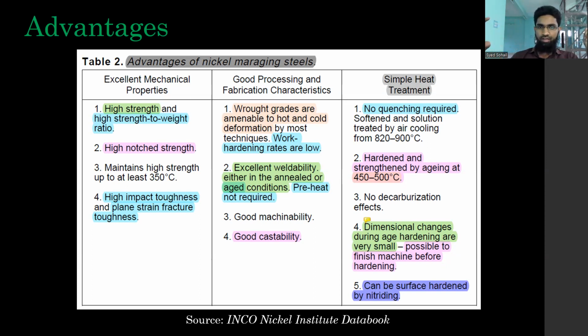You have no quenching required. Once it is solution treated or aging treated, you cool it through air cooling and not water quenching or oil quenching. Softened in solution treatment by air cooling, as mentioned, 820 to 900 degrees centigrade is the range for solution treatment, but no drastic quench. It is hardened and strengthened by aging at 450 to 500. This is the general range of aging heat treatment. Simple, as we can see. And the time is, as I mentioned, 1 hour, 3 hours, 5 hours, 6 hours, and also 12 hours. But there is a reversion of austenite issue, so generally it's kept to 5 or 6 hours. No decarburization because of the extremely low amount of carbon.